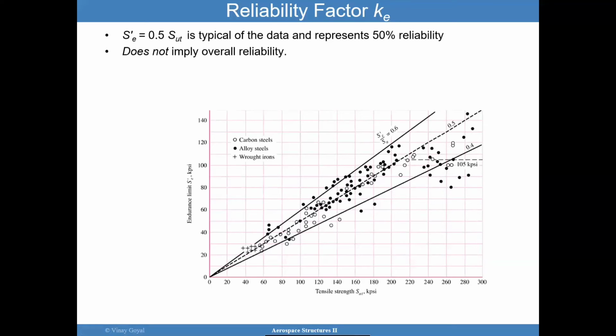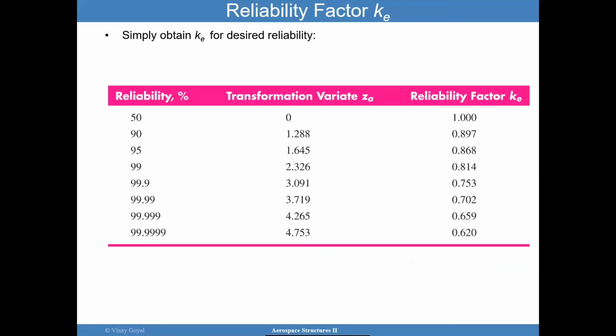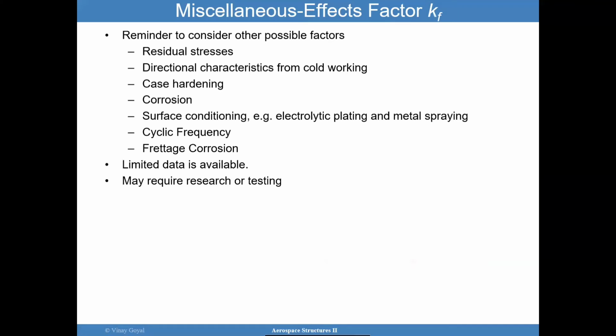So SE prime equals 0.5 SUT is typical, but represents 50% reliability. It does not imply overall reliability, which is an important aspect here. So at 50%, K is 1, and at 90%, K is 0.897, and so forth. So K needs to be calculated using this reliability table. There are other miscellaneous effects like residual stresses, cold working, hardening, corrosion, cyclic frequency, and so forth.